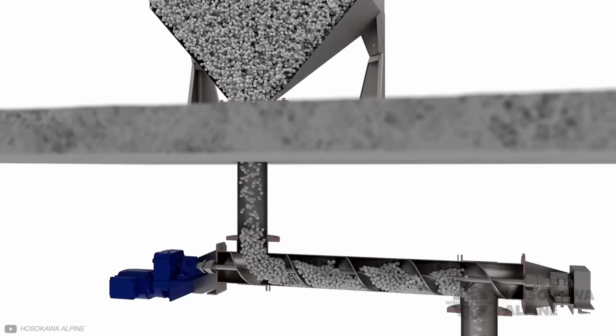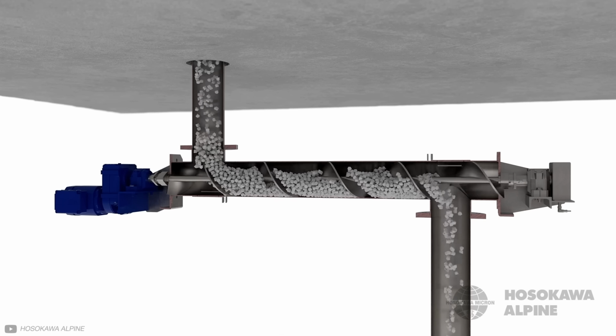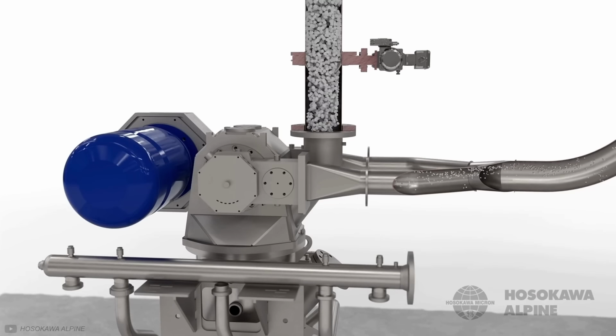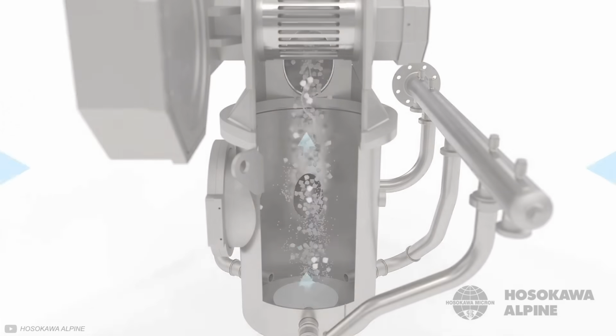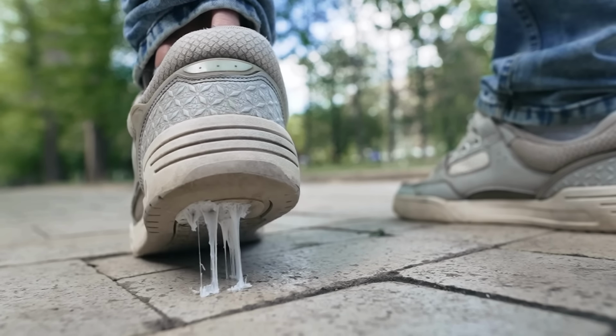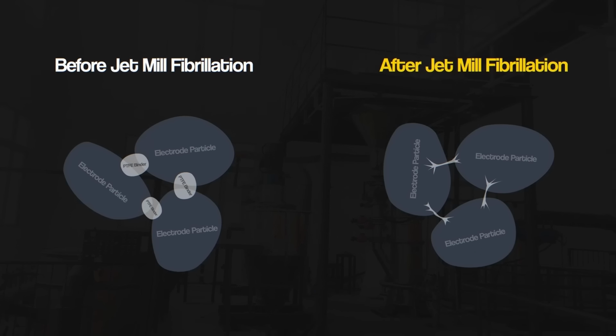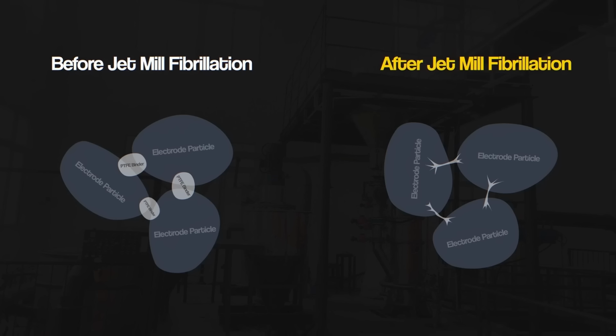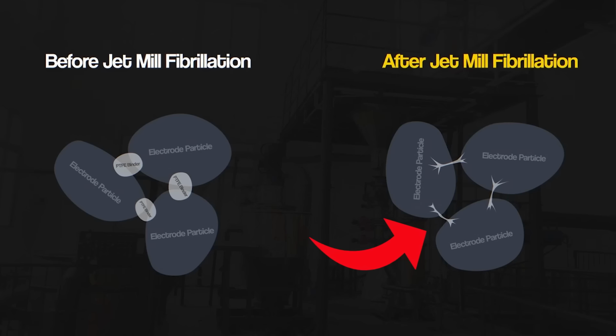I read a patent from the company Maxwell Technologies, which was later acquired by Tesla, and it sums up this process really elegantly. They take the dry electrode powder and the PTFE binder and blast it through a jet mill, where high pressure air causes the particles to collide with the surface at high speed. The shearing force from these collisions causes the binder to stretch out into a web of fibers, a bit like pulling a piece of chewing gum until it goes all stringy. And these fibers wrap around and bind the active electrode particles together, creating a self-supporting, dry film without a single